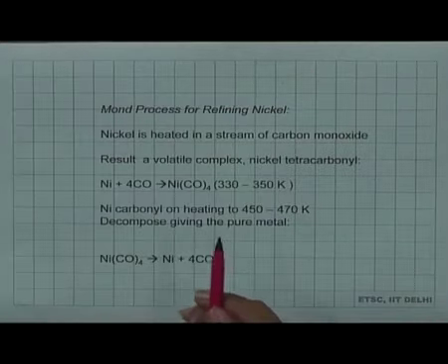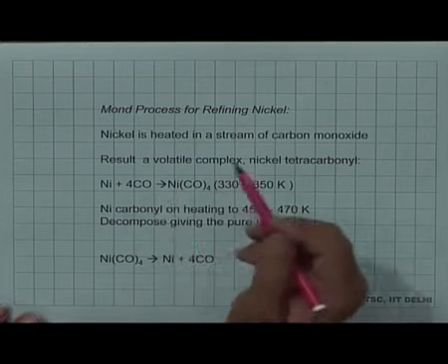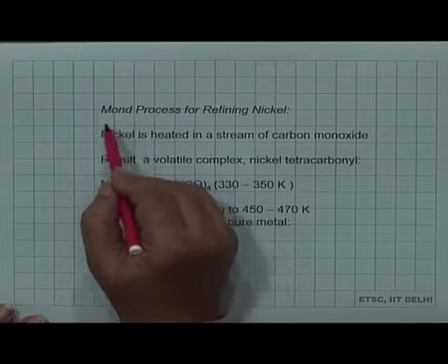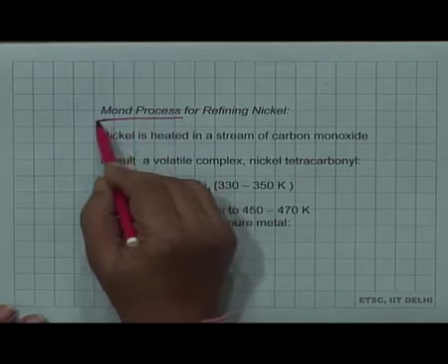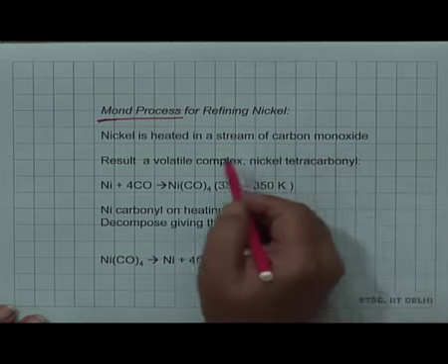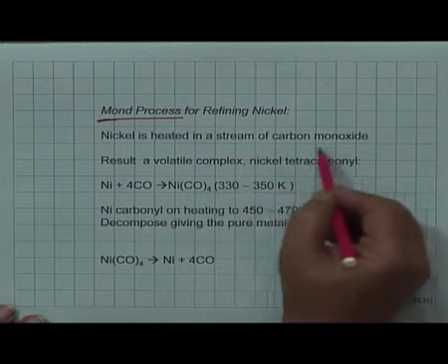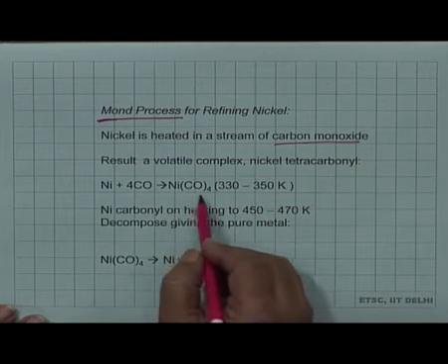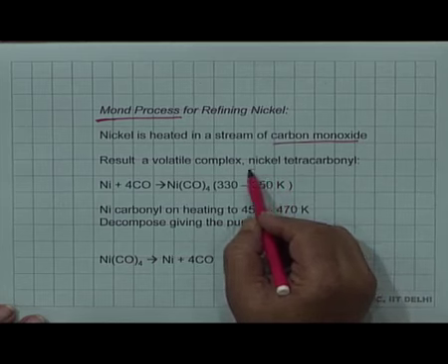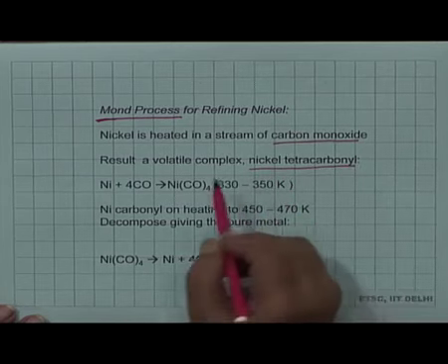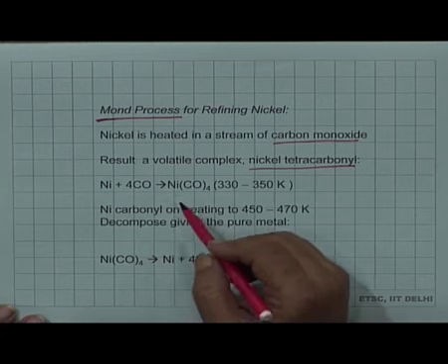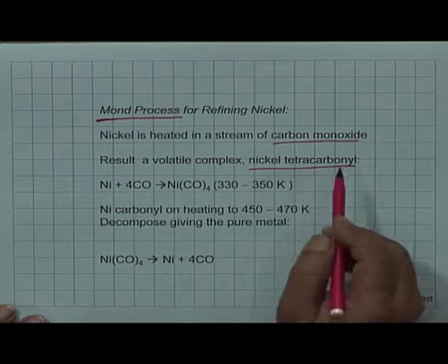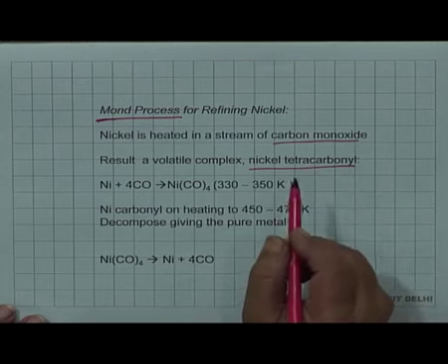As I told you, for the first time vapor phase refining was used for nickel, and the process is called Mond's process. Nickel, if heated in a stream of carbon monoxide, is converted into nickel carbonyl, or more specifically nickel tetracarbonyl. No other metal generally found as impurity with nickel gives any carbonyl when reacted with carbon monoxide. So the first condition is followed.